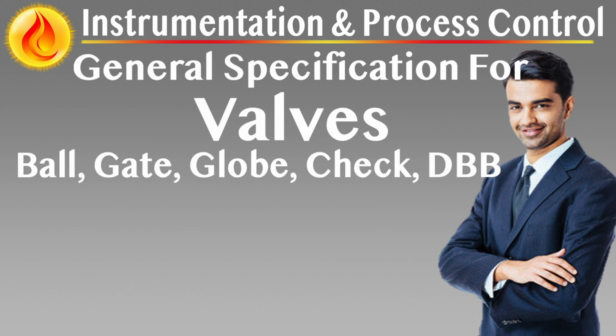For ball valves in gas service and pressure classes 900 and above, a grease injection point shall be provided for the lower trunnion in 2-inch and 3-inch valves, and on both upper and lower trunnions for 4-inch and larger sizes. Ball valves intended for use in high pressure or sour service shall have welded overlay of CRA, e.g. Inconel 625, on all wetted surfaces of carbon steel components, including ball faces, stem seals, and seat pockets, to resist corrosion from trapped moisture and aggressive media.